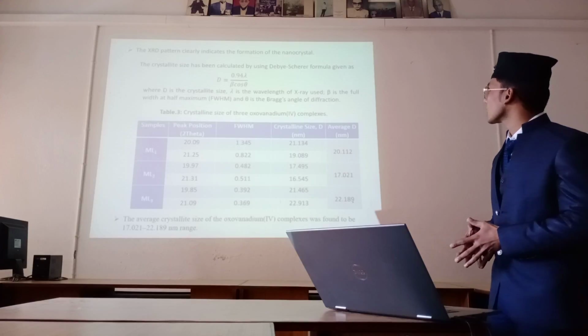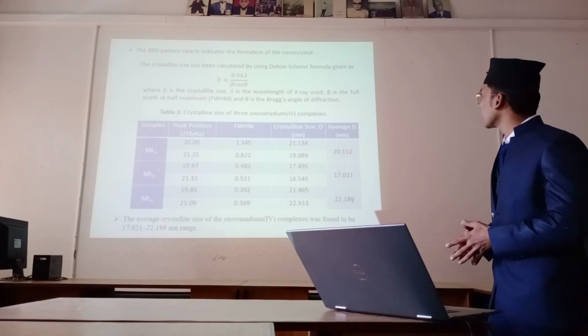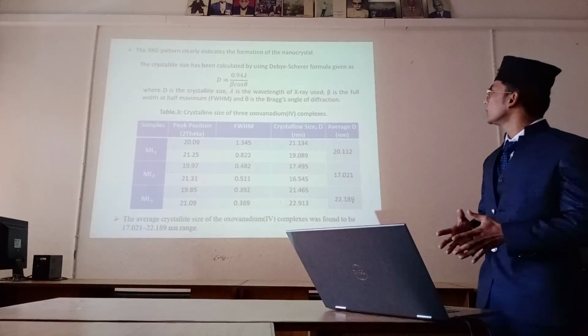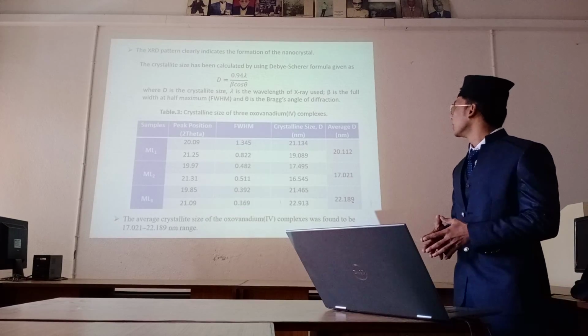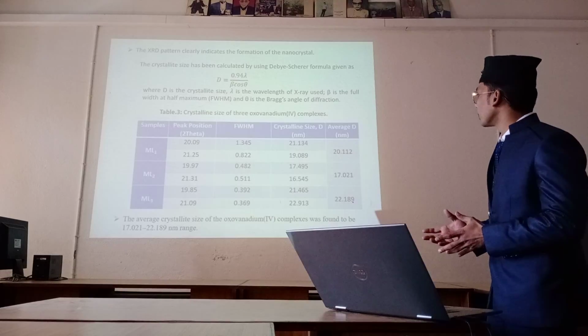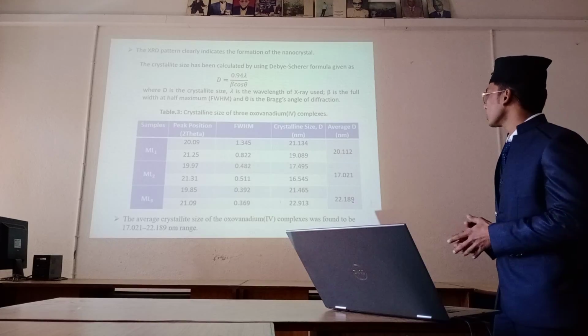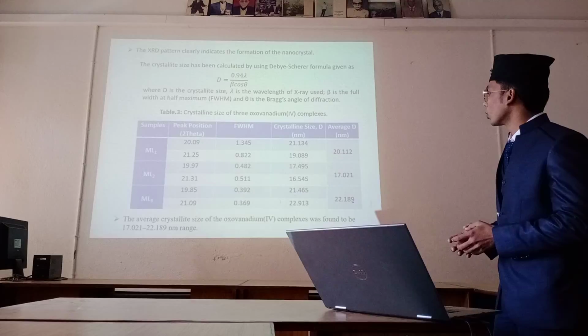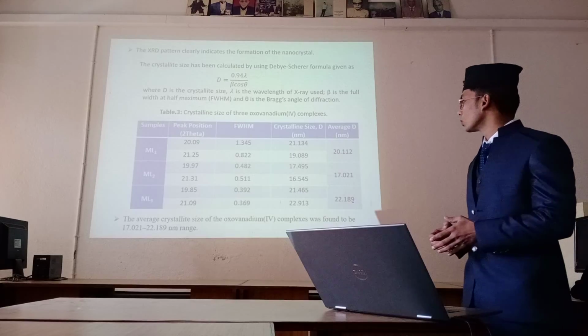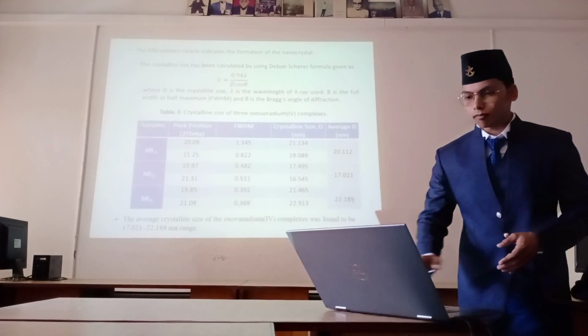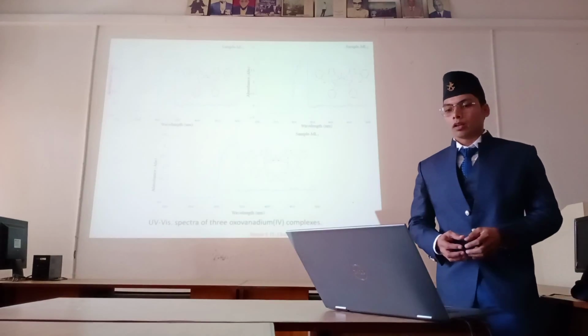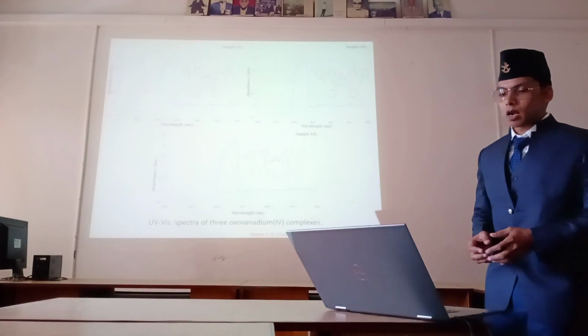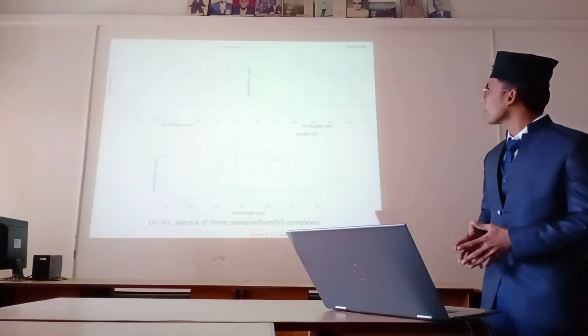The crystalline size has been calculated by using the Debye-Scherrer formula given here. Table 3 shows the crystalline size of the 3 oxovanadium IV complexes. The average crystalline size of the oxovanadium IV complexes was found to be nearly in the 17 to 23 nanometer range. And here we can see the UV-visible spectra of the 3 oxovanadium IV complexes.